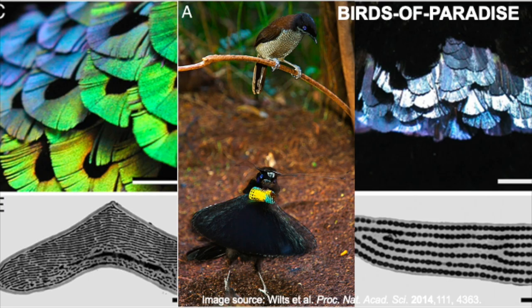In contrast, breast feather barbules contain much smaller melanosomes, around 120 plus or minus 15 nanometers in diameter, with an interlayer spacing of roughly 230 plus or minus 20 nanometers. In addition, the layers in the breast barbules are skewed, producing a boomerang-shaped cross-section. These markedly different barbule morphologies give rise to distinct spatial and spectral reflection properties.